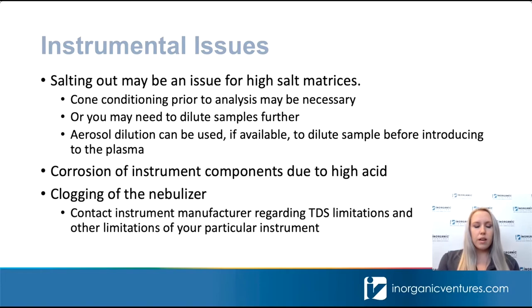Another issue that you need to be aware of is that if you have a high acid concentration in your solutions, this could cause unnecessary wear on your instrument due to corrosion, especially high hydrochloric acid matrices. There are issues for corrosion, so just be aware of those and make sure that if you need to dilute your sample further that you're doing that. Also, clogging of the nebulizer could be an issue depending on your instrument. So we recommend contacting your instrument manufacturer prior to conducting your analysis to ensure that you're within the limitations for total dissolved solids or any other type of limitations of your particular instrument.